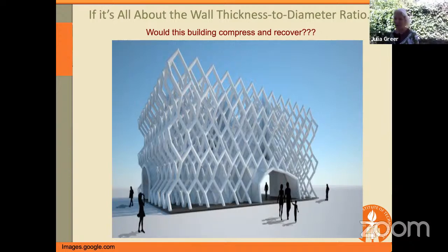So why not? The mechanics tells us that as long as the t over d is below this critical ratio of 0.03, we should be able to observe this recoverability, but we don't observe this recoverability in large scale, of course, right? So how does the size effect manifest itself here? So it turns out that the answer is all in defects. Of course, brittle materials all fail at flaws.